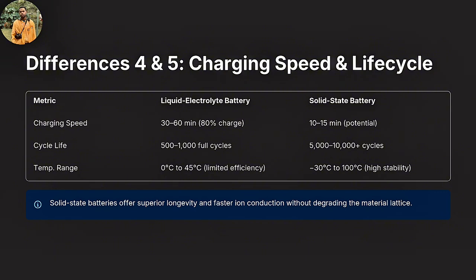Cycle life is even more dramatic. Conventional batteries degrade after 500 to 1000 full charge cycles, roughly 3 to 5 years for daily use. Solid-state batteries can withstand 5000 to 10,000 or more cycles. That's 10 times longer. And temperature range: SSBs operate reliably from minus 30 to plus 100 degrees Celsius, while liquid electrolytes are constrained to 0 to 45 degrees.